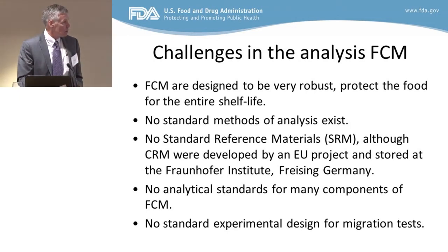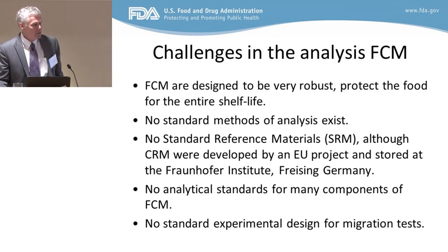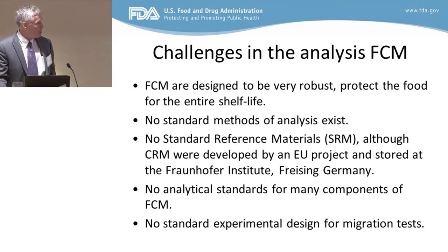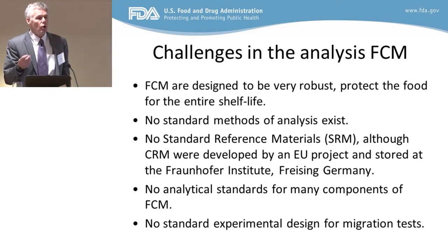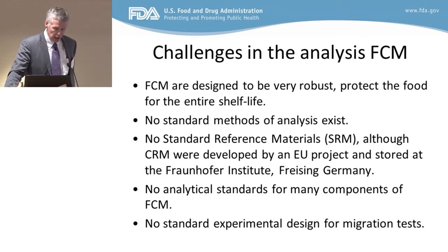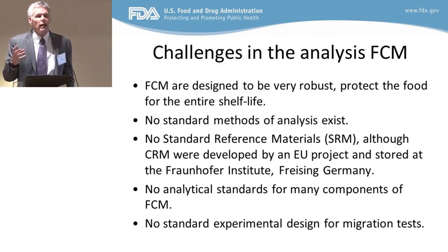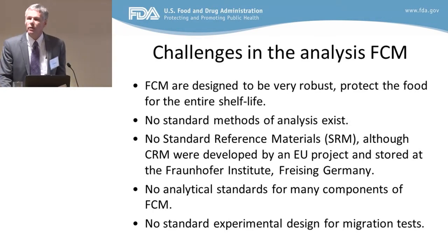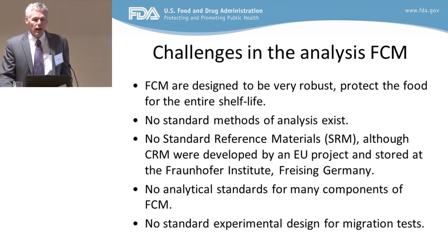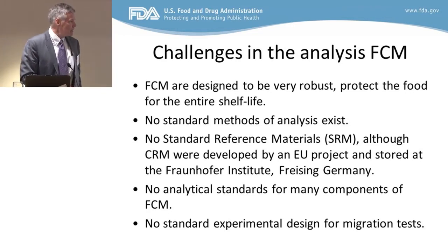There are no standard reference materials that you would find at NIST so someone can actually be proficiency-tested to see if they can do the analysis correctly. About 2002, there was a project in Europe where they actually made some certified reference materials to help people qualify their labs. Those standards — there are probably about six of them — are still stored at the Fraunhofer Institute in Freising, Germany. They include some antioxidants and monomers. Additionally, in a lot of cases there are actually no analytical standards that you can buy to confirm identity, which from an analytical chemistry point is a problem.